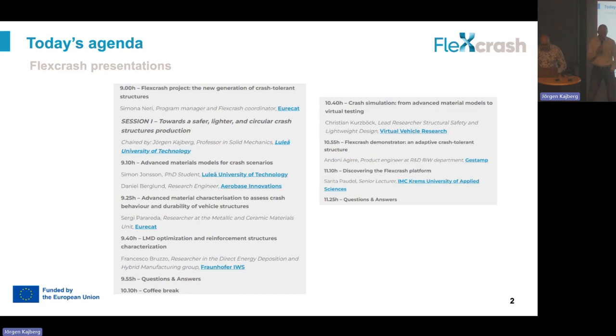Mm-hmm. But I've used thick shell elements for composites for a couple of years, so I'm pretty used to making layered properties, and it works even if you have very uneven properties through the thickness. So we will test it more, and I will give an answer later on how robust it is. Especially regarding normal shell elements, solid elements are fine in certain ways, but in a full vehicle crash, solid elements are not so useful regarding time steps. No. But I would say that with this element, you can definitely keep a bigger time step in comparison with the solid model. As in the example here, where we really need to resolve this outer layer, another solution than a solid or a thin shell is required. It doesn't work with thin shells. Okay, thank you.